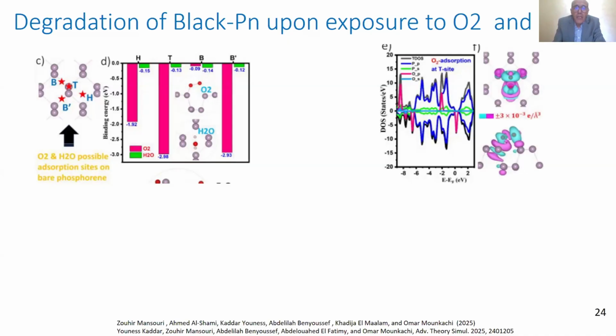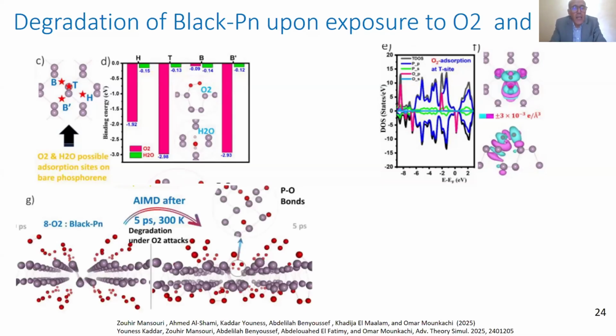But to look for stability, we have to do molecular dynamics and see if this adsorption leads to a bond between oxygen and phosphorus. Using molecular dynamics with 5 picoseconds at room temperature, we can see that oxygen adsorbs on the surface and makes a bond between phosphorus and oxygen. And this is the first origin of the degradation of phosphorene in the presence of oxygen.